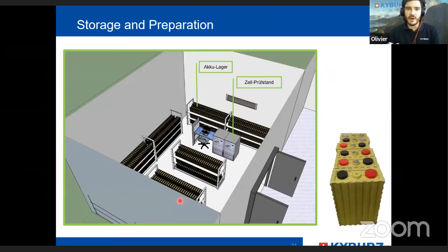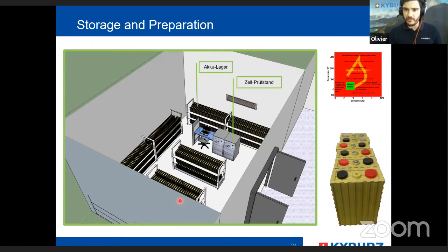We start with the storage and preparation of the cells. A lot of people think that's not a very important step, but I showed you before the slide with the range of the cells. So we have a special way to discharge the cells to 2.0 volt. With this method, we are taking a lot of energy out of the cells, but we are not destroying the cells. And for the operator, it's no longer dangerous to work with the cells. So the energy is out and we didn't destroy the cells because we stopped at 2 volts.